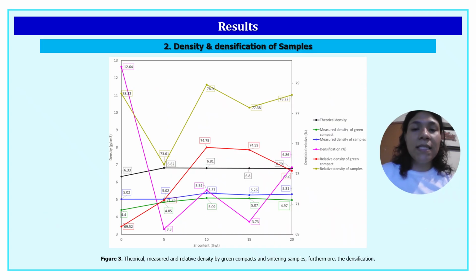Figure 3 presents the results of measured theoretical and relative density of the green compacts and sintered samples, as well as the densification percentage after the sintering process. It can be observed that the theoretical density of the samples increases for the 5 zirconium sample compared to the 0 zirconium sample. This was attributed to the addition of a denser element to the nickel titanium silver matrix. However, as the percentage of this element in the alloy increases, a decrease can be observed.